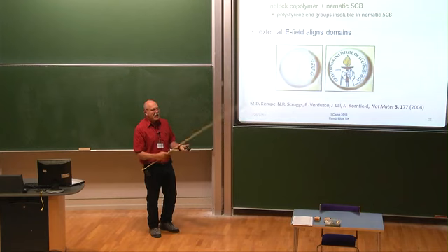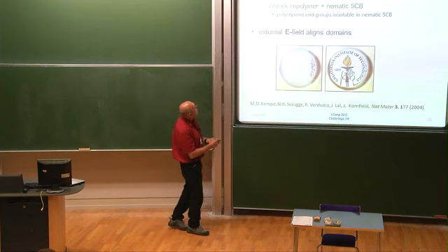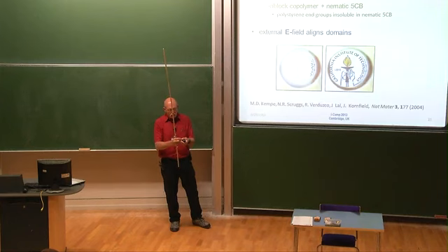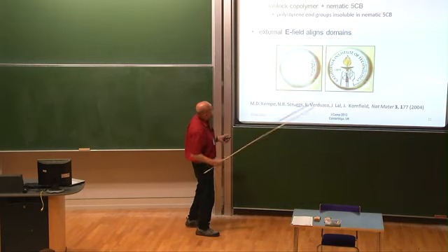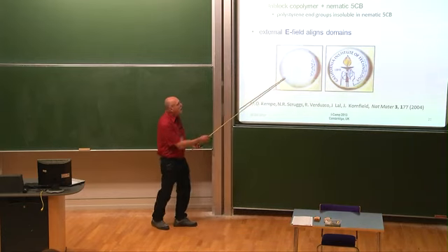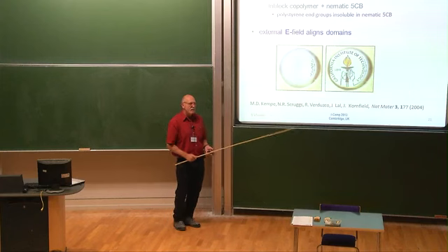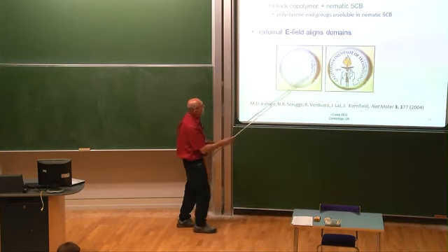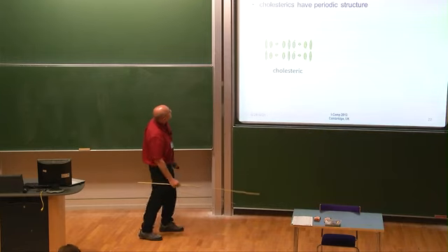But when you cooled it down, the insoluble polystyrene end groups tried to microphase separate, and they formed a physical cross-link, and so formed a physical gel. And this, again, was a polydomain material, but you could align the domains with an electric field. And so you could make a kind of scattering, non-scattering shutter.